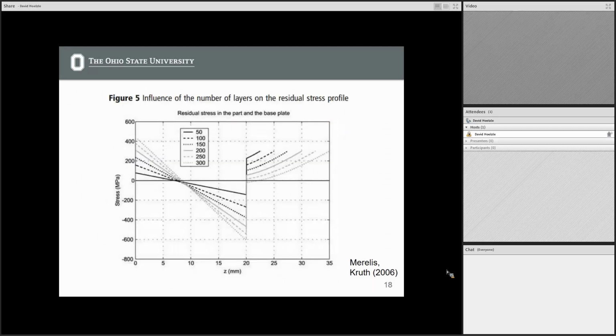So then taking a look at tuning some of these parameters and how it's going to affect our results, this is taking a look at the number of layers that you're building up, so from 50 to 300 layers. You can see that we get an increase in base plate stress. However, our maximum stress in the part, because of that assumption, is going to remain the same. But we do get a decrease in the residual stress that's at the base of the part, and that's due to that second mechanism that we talked about, where laying a molten layer on it is going to cause compressive stress in the bottom layers of the part.